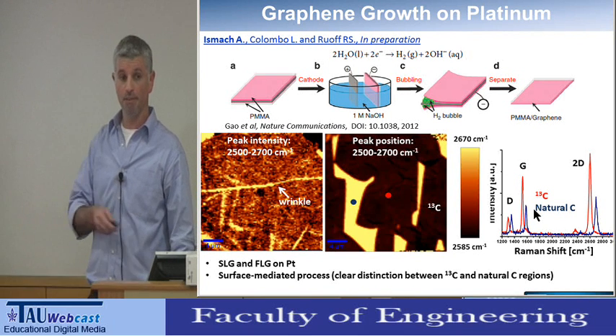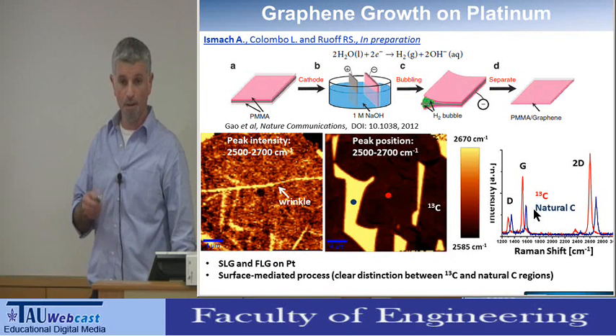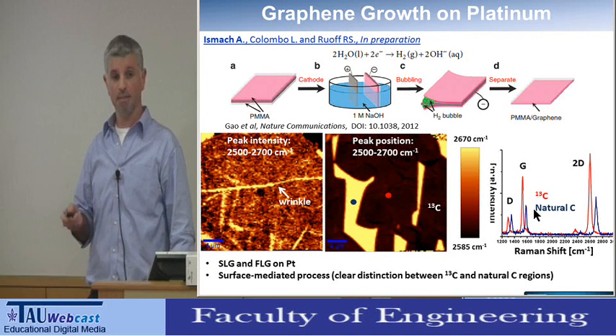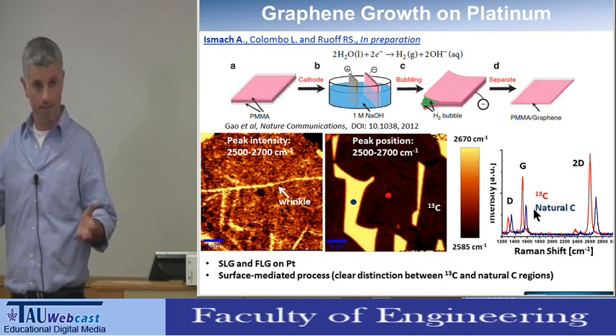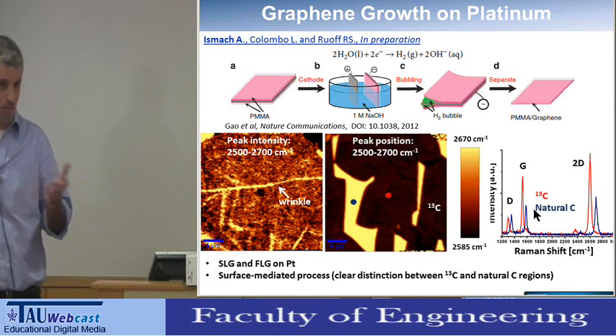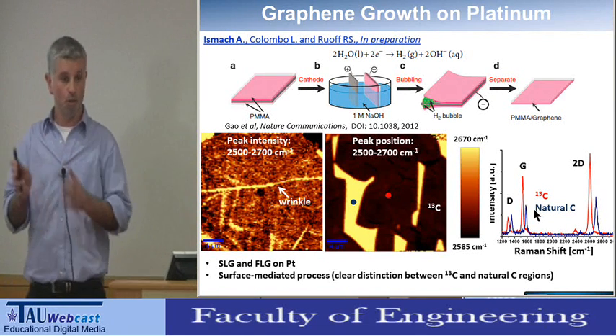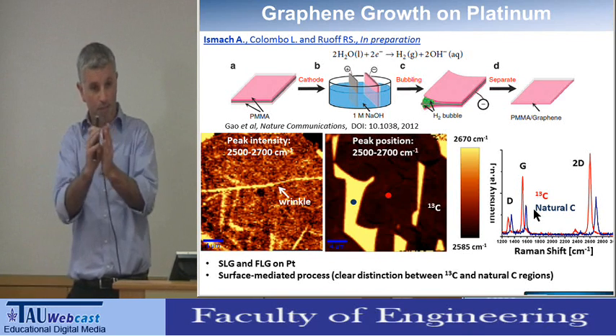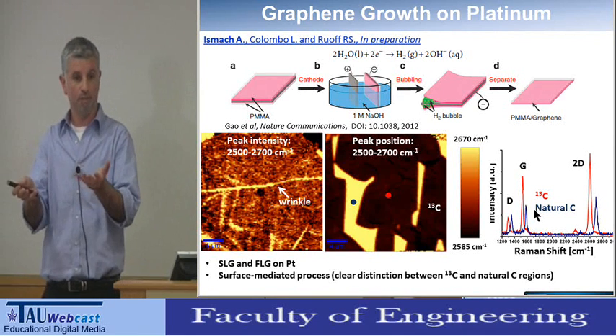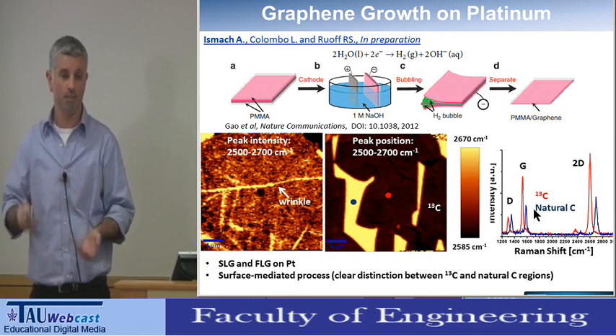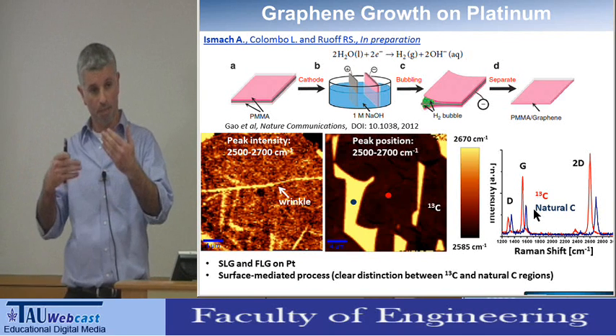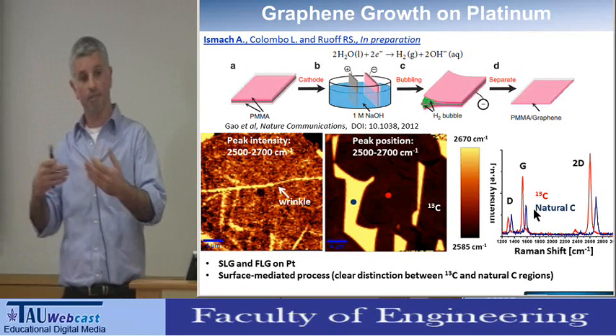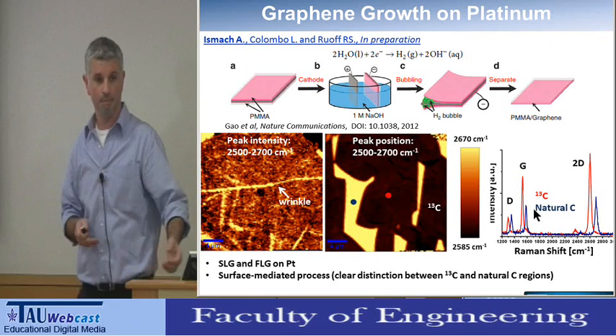No, if you have a mix, he's right. If you have a mix with 50% let's say C12 and 50% C13, you are supposed to be somewhere in the middle. Otherwise, the shift is correlated with the relative composition of the C12 and C13, which is related to the exposure of the different hydrocarbons to the surface, right?